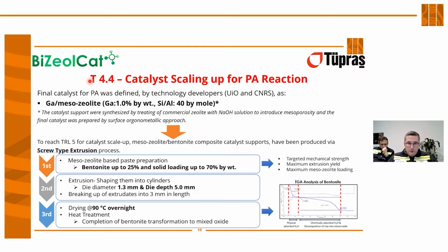So I will move to another reaction. This is called the propane aromatization reaction. The final catalyst for this reaction was defined by the technology developer, here the University of Oslo, and CNRS worked on it. Gallium doped, gallium modified mesozeolite with nearly 1% by weight of gallium, and silica alumina ratio of 40 by mole. The catalysts were synthesized by treating commercial zeolite with sodium hydroxide solution to introduce mesoporosity.